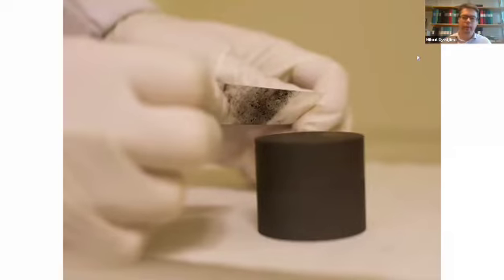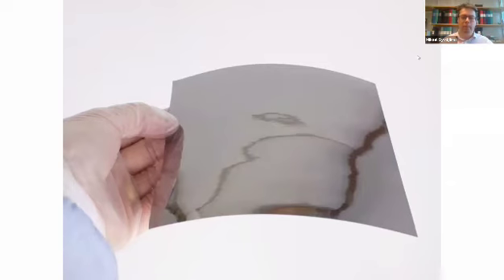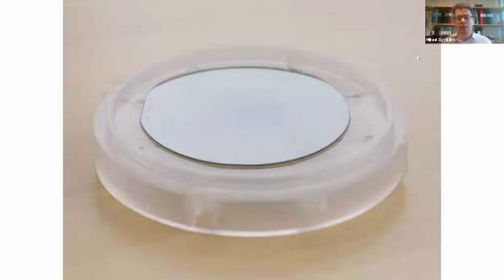And in comparison, graphene can be made either as flakes. Here is an example: when you have graphite and the Scotch tape method, you tear off pieces and make them thinner and thinner, and at some point you will have graphene flakes. Another method is to use metal foils with a carbon-containing gas, which gives a carbon layer on the metal foil. Here you can get to a large area, but it's still difficult to get good quality, and you need to transfer it using some polymer, which is used for electronics and so on. And then the third method is actually coming back to the graphitization of silicon carbide.